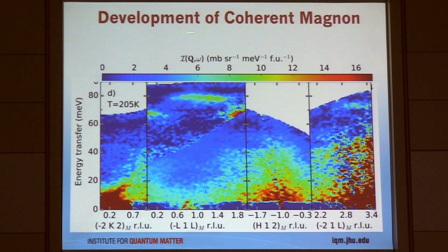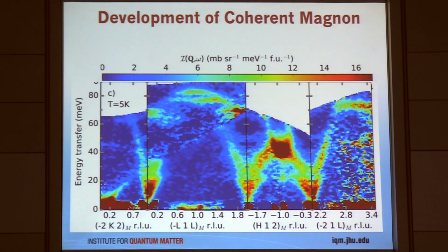And here is shown the inelastic magnetic neutron scattering data in the paramagnetic insulating state. So quite broad features are seen extending over a large range of energy transfer. This is actually quite similar to what we typically see in strongly frustrated spin systems. Very, very broad features both in momentum and energy. A little dull, you could say, but when we see it, we know that we're dealing with some frustrated spin system.